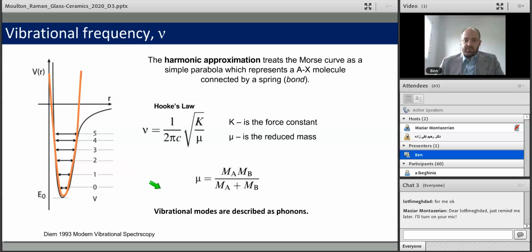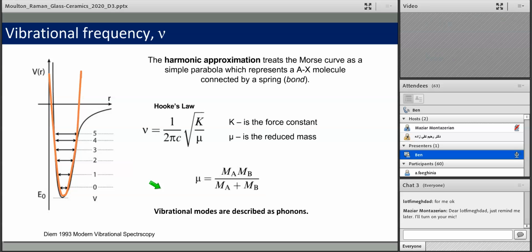If we step back and just consider a pure diatomic molecule, such as a silicon-oxygen bond, as they move away from the minimum condition, as you stretch them, they will gain some potential energy. And we can model the expansion and contraction of this bond using Hooke's law. That tells us that the frequency of these vibrations is related to some constants, pi and the speed of light, multiplied by the square root of k over mu, where k is the force constant, which you can think of as the strength or covalency of the bond, and mu is the reduced mass, which is the product divided by the sum of the masses of the atoms involved.